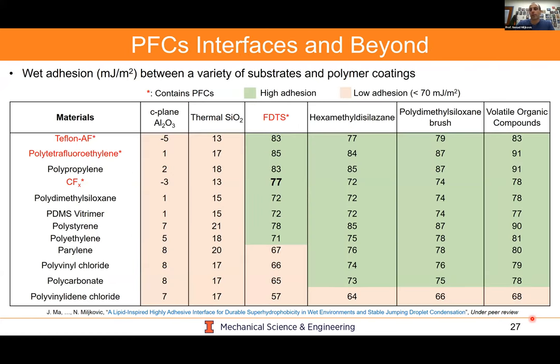And again, if we were to look at different materials, you don't have to use FDTS and CFx. You could use a range of fluorinated or non-fluorinated materials. You could use a range of different organic compounds to form that base covalent layer with the substrate. And you could see here, the green is what will work and give a very high wet adhesion. And these combinations here have fairly poor wet adhesion and may not work for dropwise condensation applications.